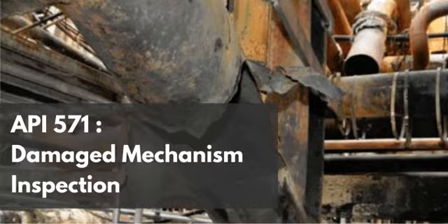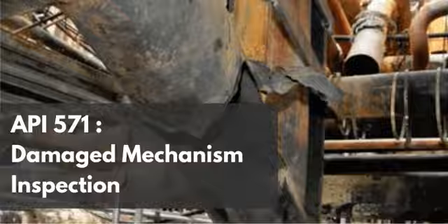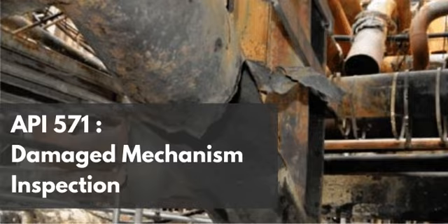The high temperature strength and creep resistance that the molybdenum and chromium provide do absolutely nothing to stop the chemical dissolution of the metal. So you can have a pipe that is incredibly strong, that won't stretch or deform under massive high-temperature pressure, but it has zero chemical armor against this specific degrading amine solution. Exactly. You cannot conflate mechanical high-temperature strength with chemical corrosion resistance. They are two entirely different metallurgical properties. That's a huge distinction. It is. In the face of severe amine corrosion, your highly expensive, incredibly strong 9-chrome-1 moly low-alloy steel might corrode and thin out just as disastrously and just as quickly as your basic off-the-shelf carbon steel. That is a massive paradigm shift for anyone assuming an upgraded alloy automatically means an upgraded lifespan across the board.